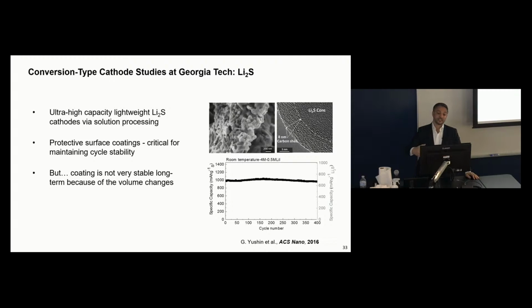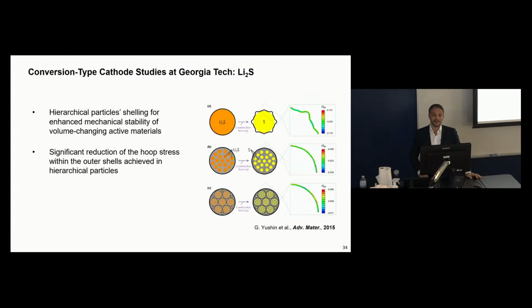And so again, if you have this nanostructured material with core-shell protection, you can get some decent stability to some degree. Unfortunately, the coating is not very stable. During charge and discharge, the particles change volume, and typically the coating fails at some point. Then you start to have dissolution. And the problem becomes particularly important for high loadings, when you have thicker electrodes. You have more dissolution products, you have resistance rising, and so forth. And then you have to use some special electrolyte to try to minimize the damage. Some of the electrolytes have this kind of self-repair mode. Once you have this breakage in the shell, you can try to repair it. It's not very effective, though, but it helps.